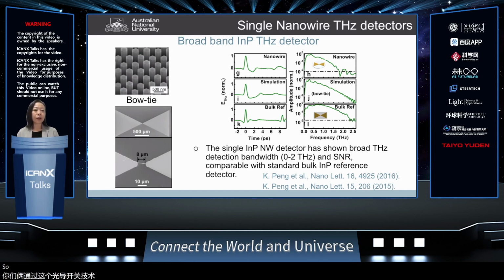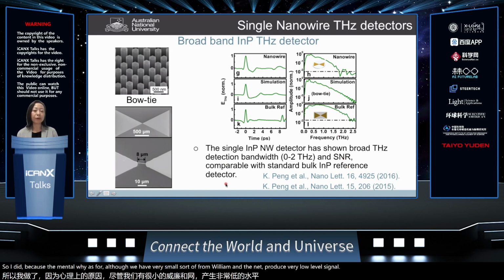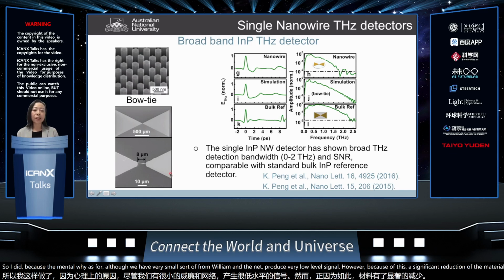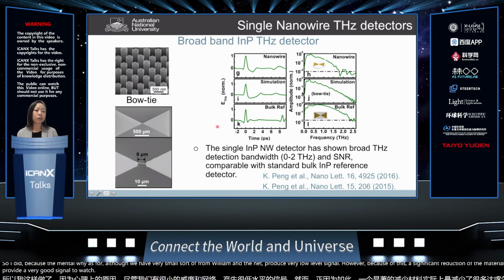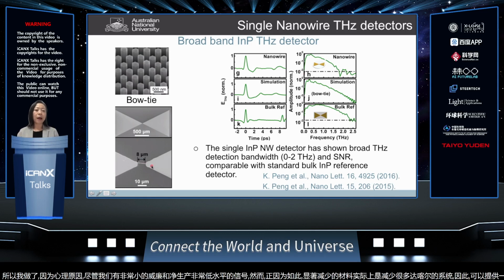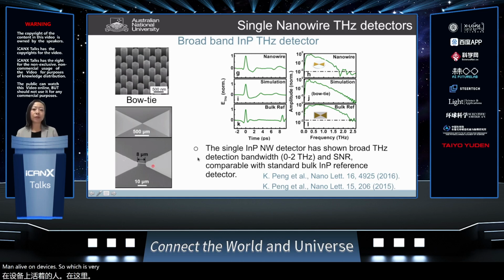So because the nanowire has a very small volume, it produces a very low level of signal. However, because of this significant reduction of material, it actually reduces a lot of the dark current in the system, and thereby can provide a very good signal to noise ratio from this single nanowire device. Which is very, very interesting.